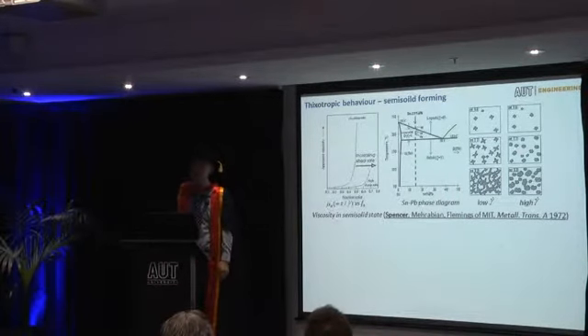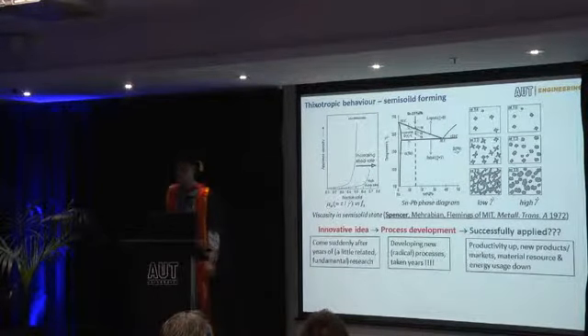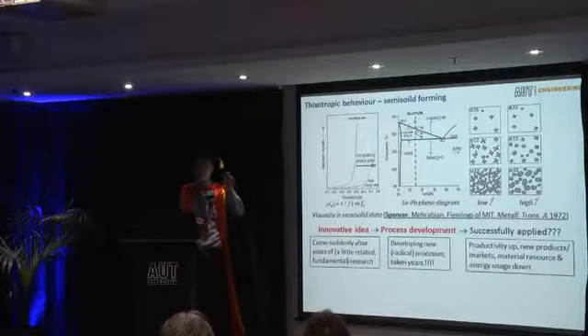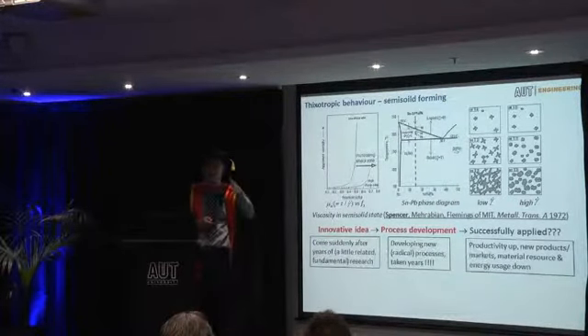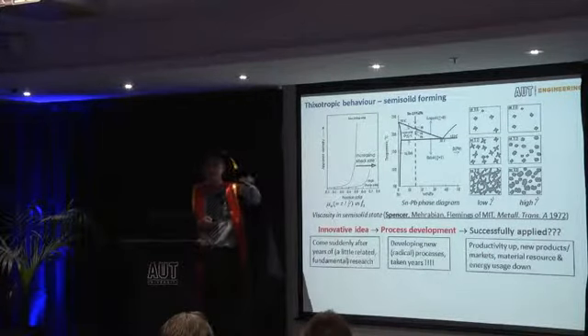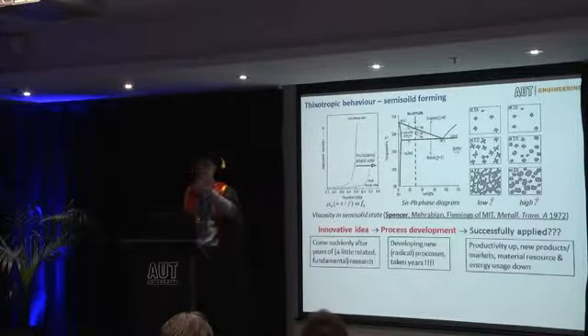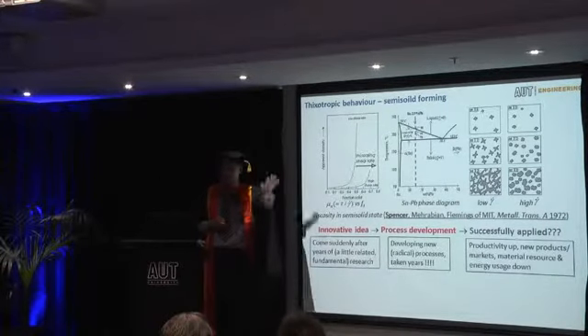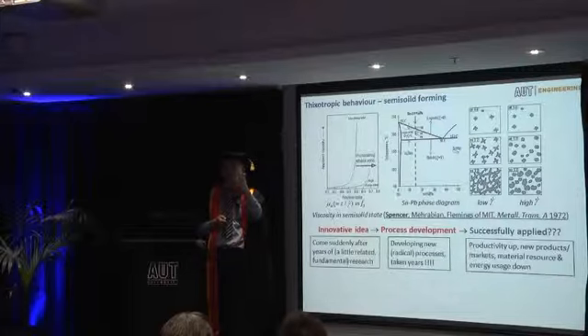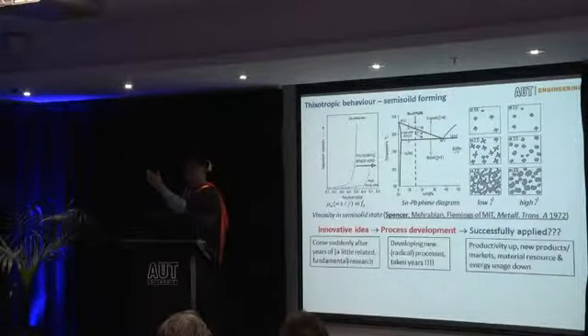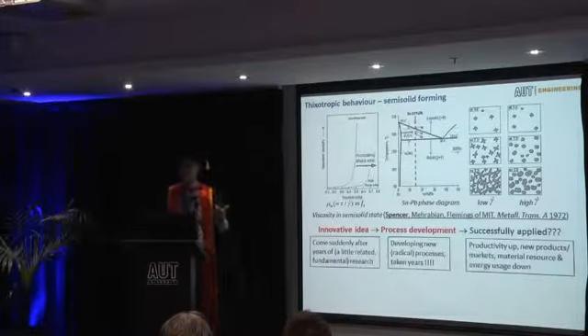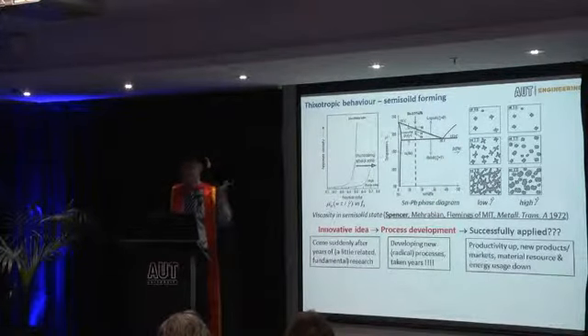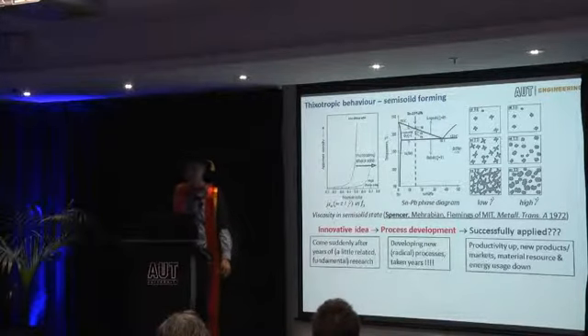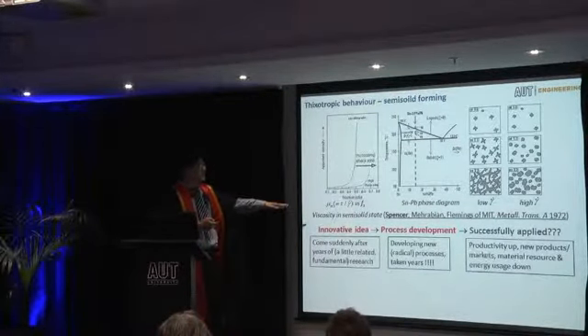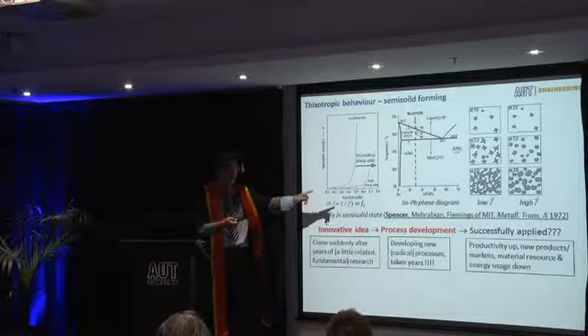This behavior was actually discovered by a PhD student at MIT in the 70s. He was doing experiments looking at the behavior during solidification in the semi-solid state. He stirred the melt, and he found that if you keep stirring at high speed, the apparent viscosity drops, and the so-called solid skeleton point moves to a much higher solid fraction. That's the basis for this particular process, and they realized the significance of that to industry. So they patented it, and that's when the process started. Okay, a good idea, they developed the process. Now, for many years, was it successful?